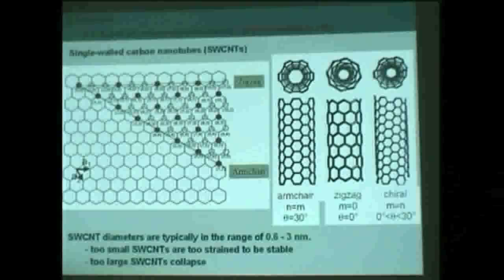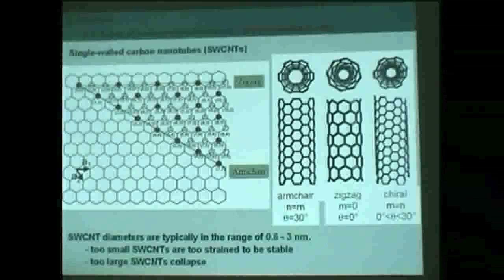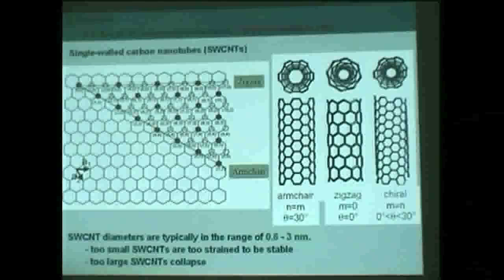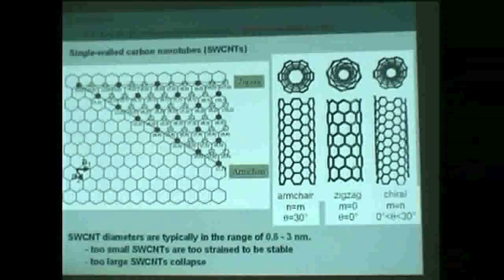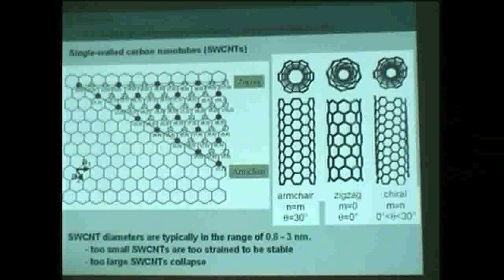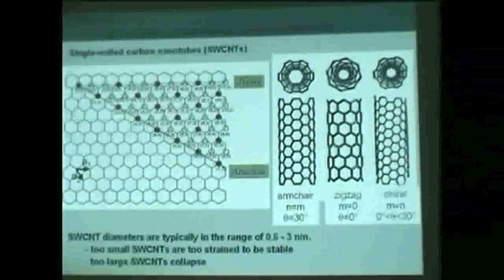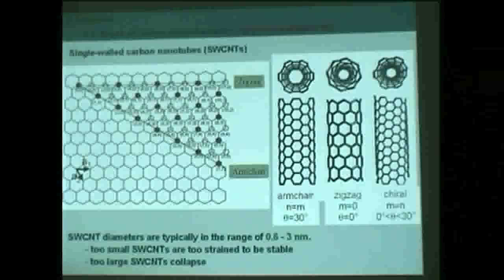Or if someone has a sheet of paper, I can show - this is a good example of a collapsed nanotube. The two sides have collapsed on themselves. At the beginning we've got the rolled tube, and then at the end it collapsed. This happens when the diameter is too large. This is why usually there are very few tubes with a diameter of more than 3 nanometers.